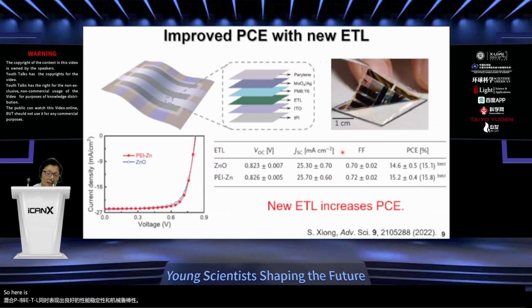Here is the performance of our ultra-flexible organic solar cells using PEI-Zn as the ETL layer. We use the state-of-the-art active layer PM6:Y6 as the photoactive layer, and we compare the conventional zinc oxide ETL and the PEI-Zn ETL. We found that PEI-Zn shows almost the same or a little bit improved PCE in comparison with the zinc oxide based conventional solar cells. And with PEI-Zn as ETL, we achieved 15.8% as the best PCE value.